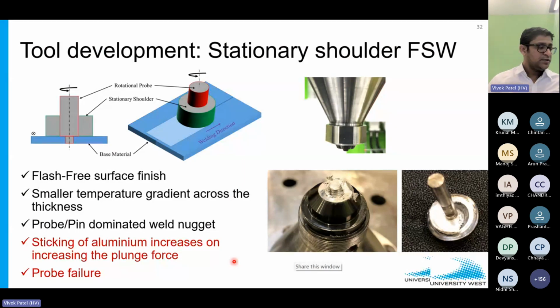Also in this work, we tried a stationary shoulder. I would say it's a new tooling system. In a stationary shoulder, you can see in this schematic that only the shoulder, the bigger diameter, remains non-rotating, so it just slides on the surface. The only rotating member is the smaller diameter, the probe. You can see the probe here. And the stationary shoulder provides a smooth surface, so you cannot have burrs and flash on the surface.